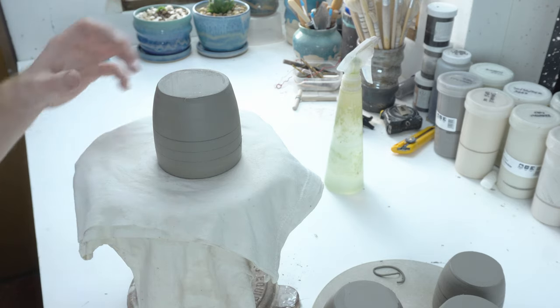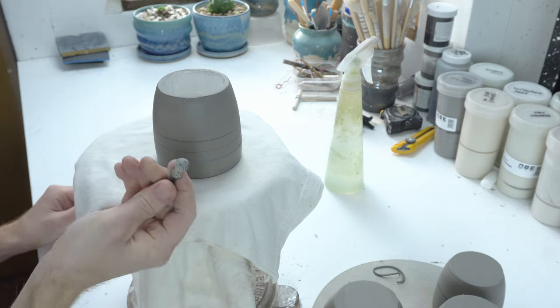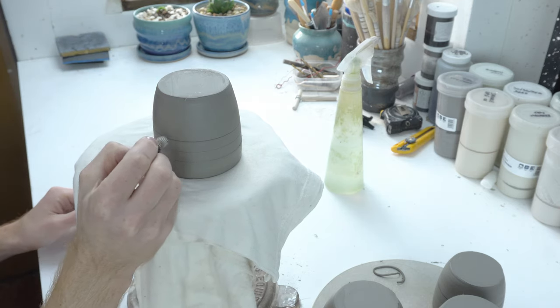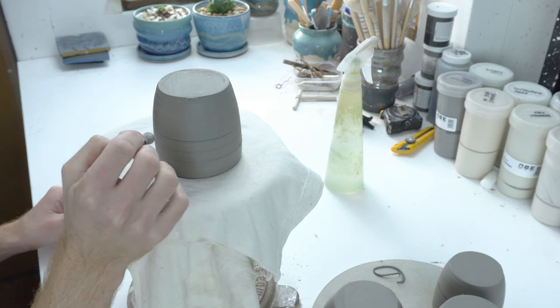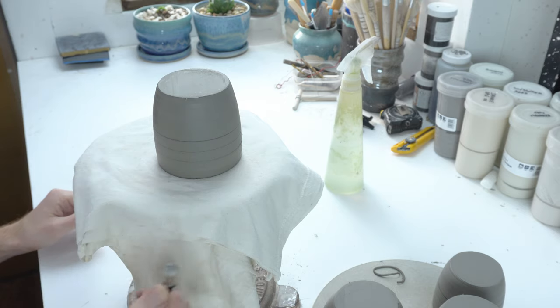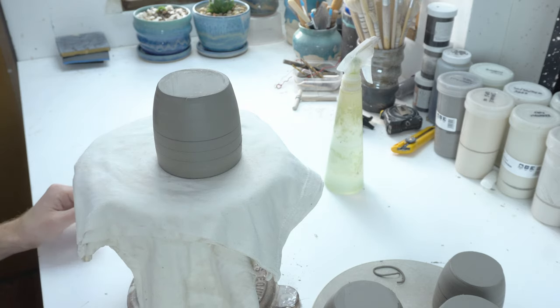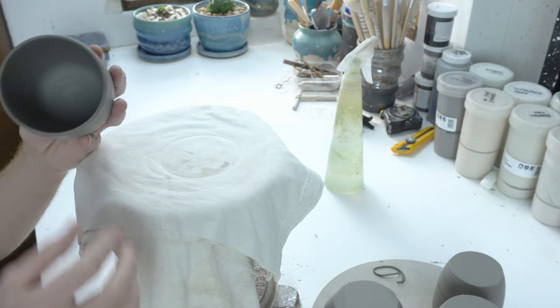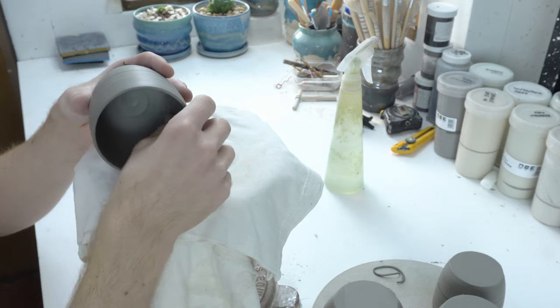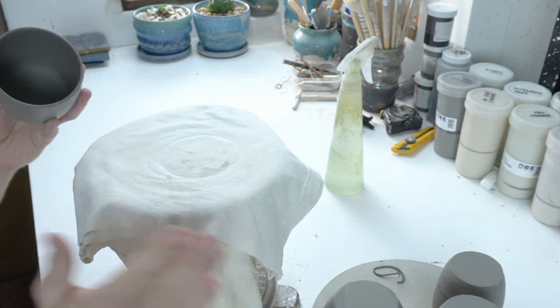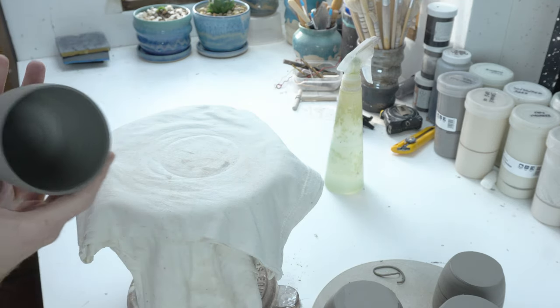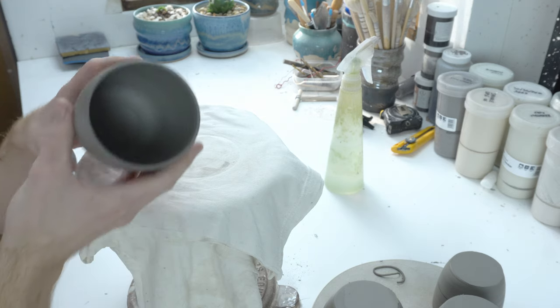The reason is that you don't want the bit to stick. If the clay is too wet, as you stamp in it will start to stick into the clay and pull when it comes back out. So if there's resistance when you pull the bit away you know the clay is too wet on the outside. And if the clay on the inside starts to crack then you know the inside is too dry. And you can balance the two of them the way you want them by firstly drying upside down.